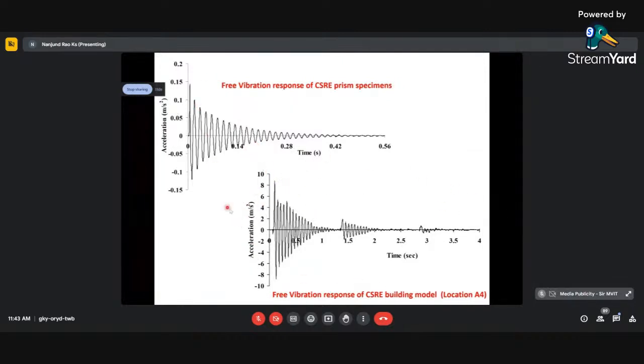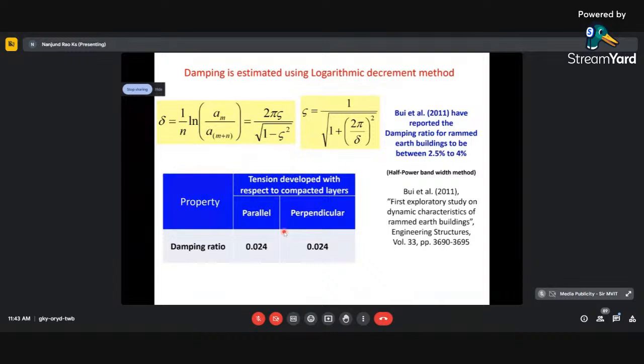This is the response of the building model. This is of the specimen, whatever I showed in the previous slide. And we were able to get the damping from these two cases from logarithmic decrement, and we found damping to be 2.4% in both directions. Damping ratio parallel to rammed layers and perpendicular, there is no change at all.